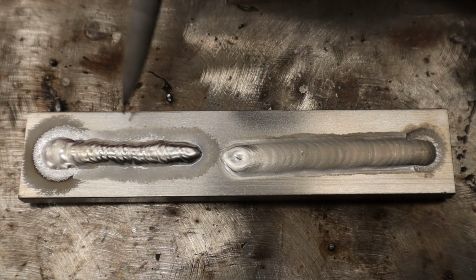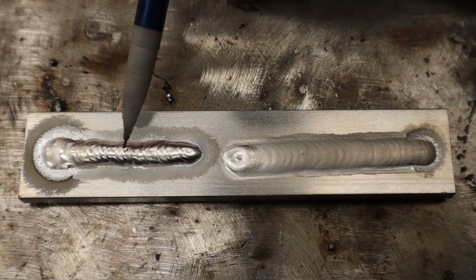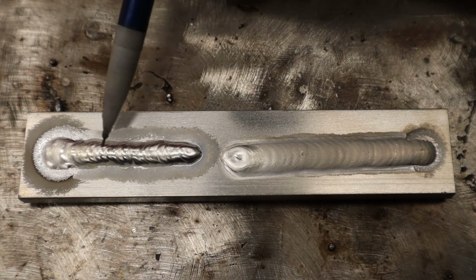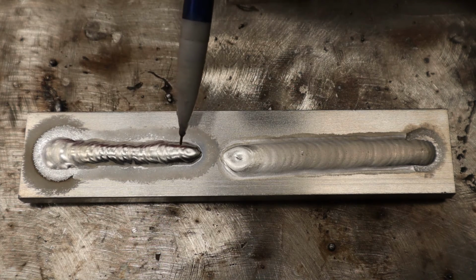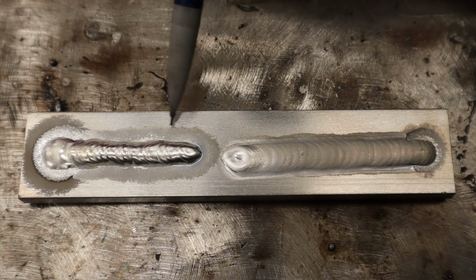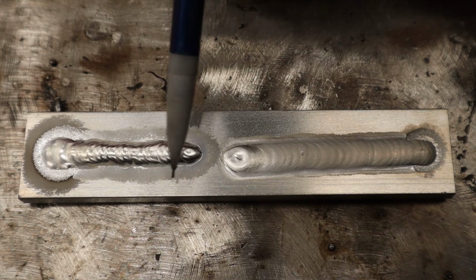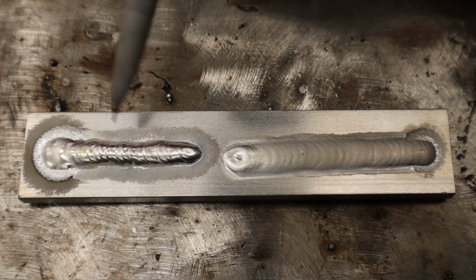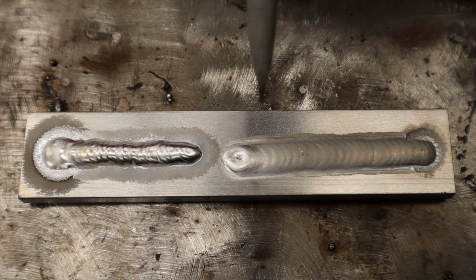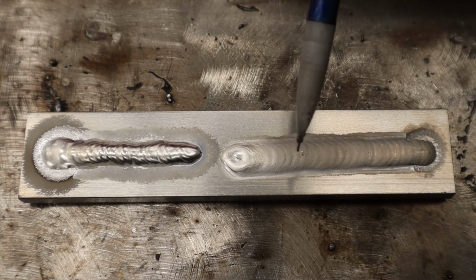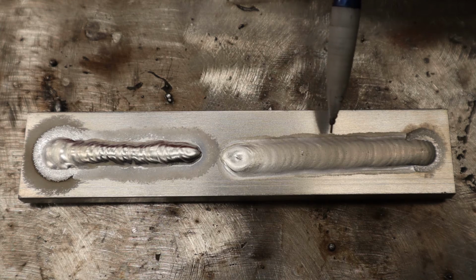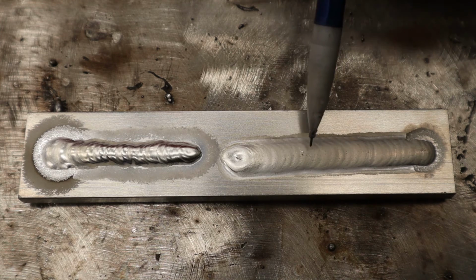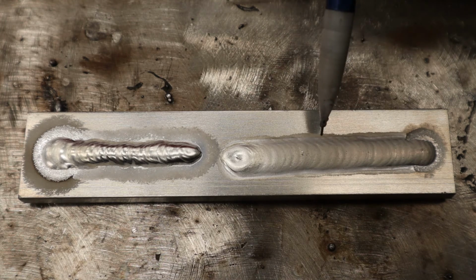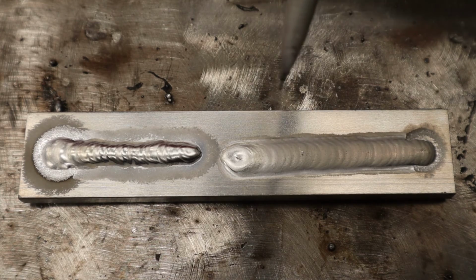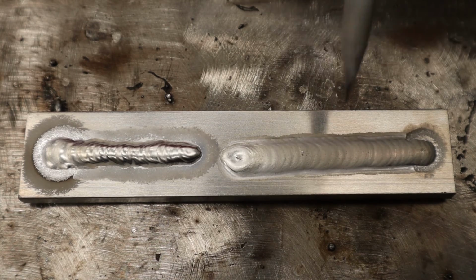Now on the max cleaning side, you can see that you do get nice clean welds. It's trying very hard to clean up any kind of contamination and kind of aluminum oxide. However, you end up with this massive etching kind of part grayed out around your weld bead because that's where it's stripping off the aluminum oxide. Now on the max pen side, you can see that right off the bat, it's got a duller look to it. And there might be a little bit of contamination, little speckles of stuff in here. And that's because it's just not getting cleaned enough and because it's focusing on trying to get the heat down.